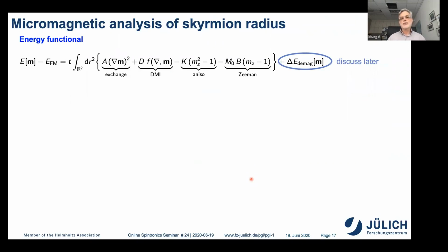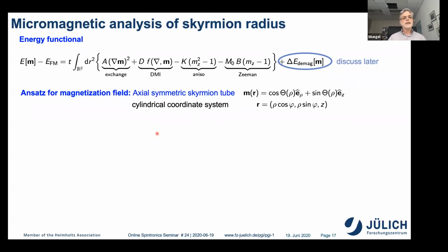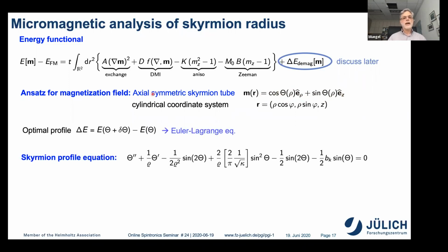Now, I would like to dive a little bit deeper into the skyrmions. I would like to make a micromagnetic analysis of the skyrmion radius. So we know meanwhile our micromagnetic energy functional. And I make the reasonable ansatz that the skyrmion is symmetric, a skyrmion tube. Therefore I write my magnetization as a function of a profile, as a function of the radius, and I assume Néel type skyrmions. And these are basically the coordinates of the Néel type skyrmions. I have to find now the optimal profile, theta, and this I do by deriving the Euler-Lagrange equations, which gives me an equation for the profile, which you see here, that minimizes this energy functional. I admit you don't have to look too much at this equation. It looks very complicated.